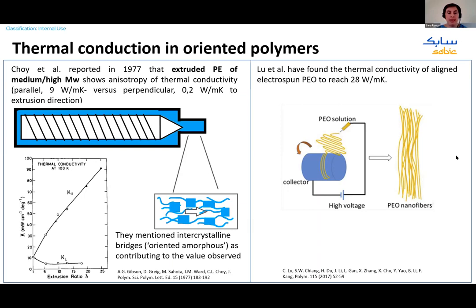They were the first to realize that this orientation is important, and they also realized that intercrystalline bridges, which they defined as oriented amorphous, bridges that interconnect crystalline parts, also contribute to the enhancement of this thermal conductivity. More recently, for example, Lu and co-workers found that the thermal conductivity of aligned electrospun polyethylene oxide could reach values up to 28 watt per meter Kelvin.